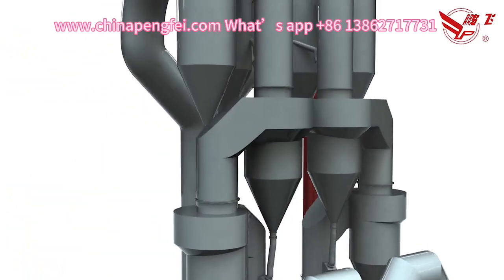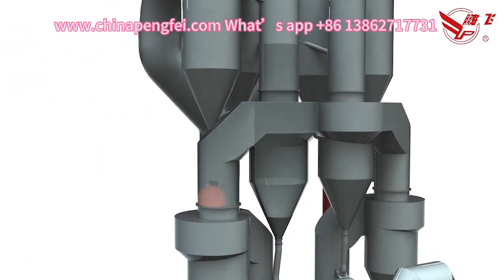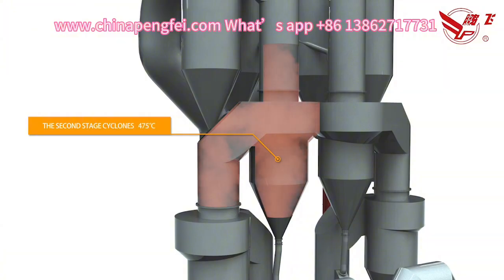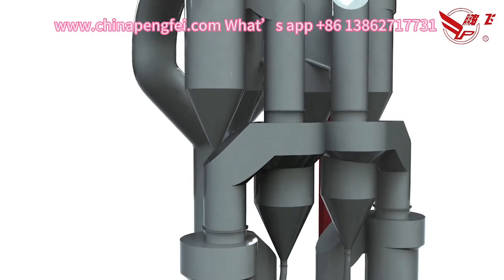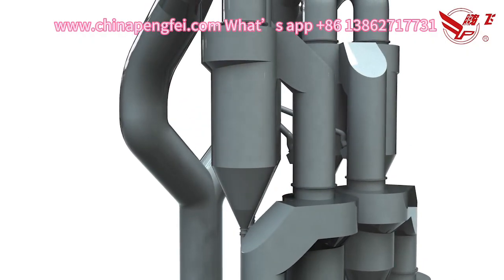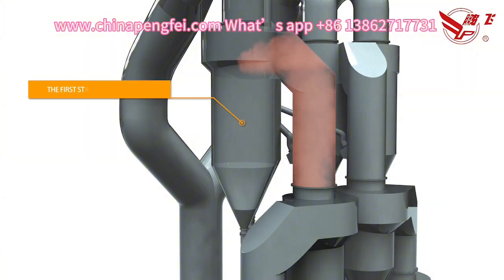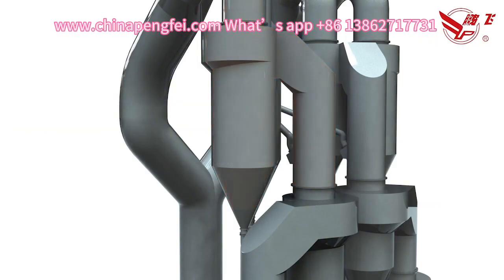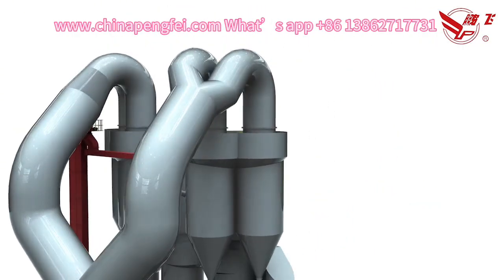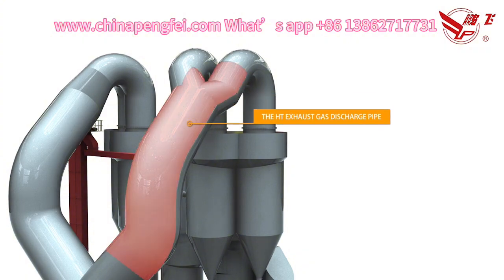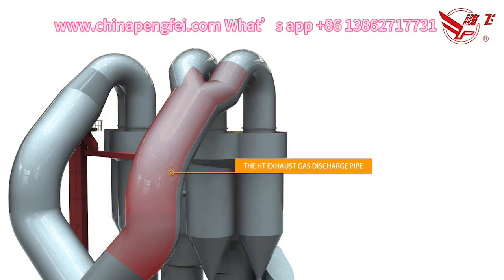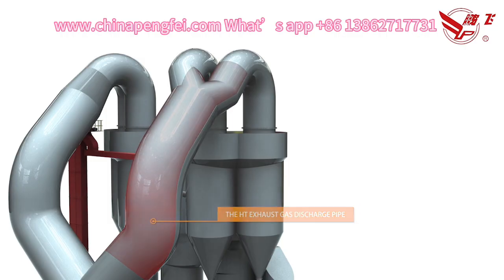The high-speed hot air continues to flow upwards and enters the second stage cyclones. The hot air temperature inside the second stage cyclones is about 475 degrees Celsius. The high-speed hot air flows upwards and enters the first stage cyclones. The hot air temperature inside the first stage cyclones is about 305 degrees Celsius. Finally, the hot air mixed with some powder enters the large high-temperature dust collector along the high-temperature exhaust gas discharge pipe.